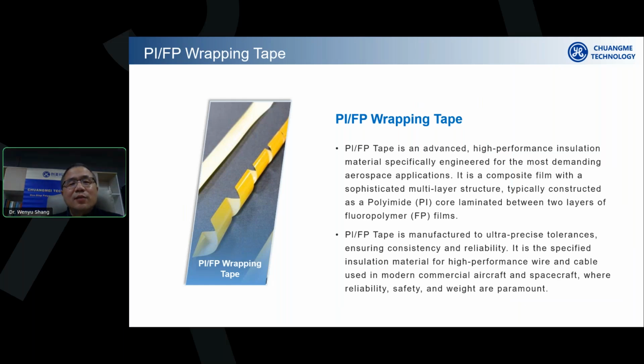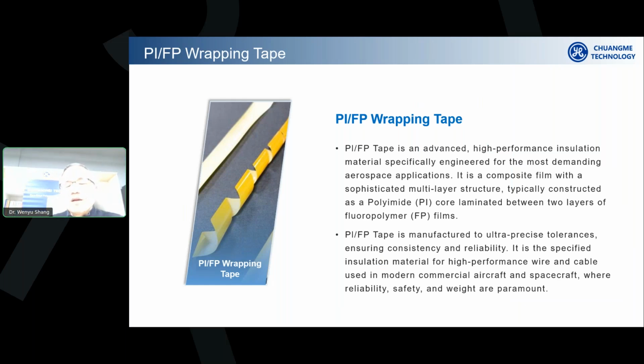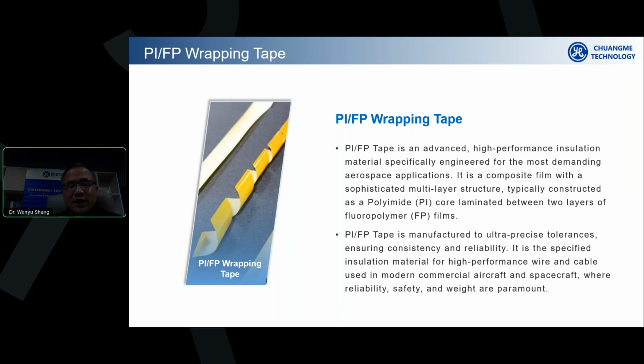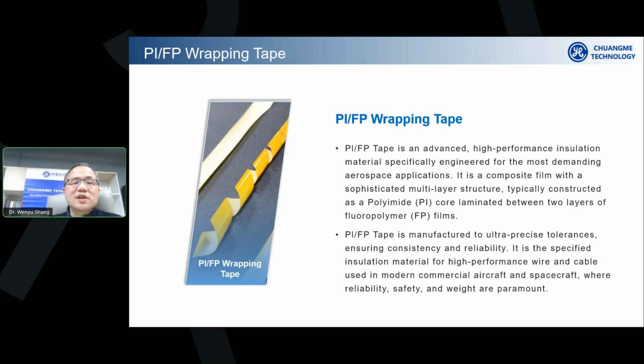This is why polyimide came into the picture and plays as the core material for the fourth generation insulation material. If we have learned any entry level of polymeric chemistry, we all know polyimide is a thermoset resin, right? The most prominent performance of polyimide is that it can resist very high temperature. Some polyimide resins can resist temperature up to over 300 degrees C. So in this application, we want the polyimide core film to sustain temperature up to 260.